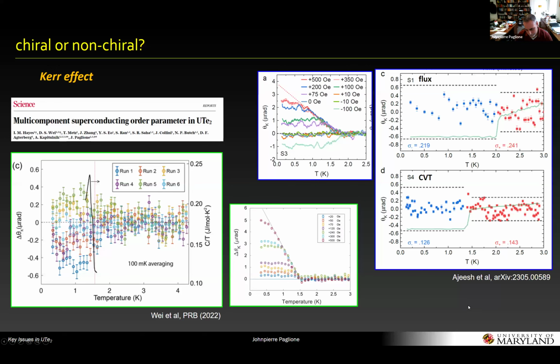In more recent work by the Los Alamos group, Sean Thomas, they repeated the Kerr effect experiments using a slightly different technique. They use a laser heating technique where they collect data points by heating and cooling the sample with a laser pulse and measuring the Kerr response, with admittedly slightly less resolution than Aaron's setup. But nevertheless, within the envelope claimed by the Kapitulnik group, they don't see any Kerr effect in samples. This is both in salt flux crystals and vapor transport crystals, so both generations. I haven't talked to Aaron lately, but he was certainly interested in trying to reproduce his experiments in higher TC samples.